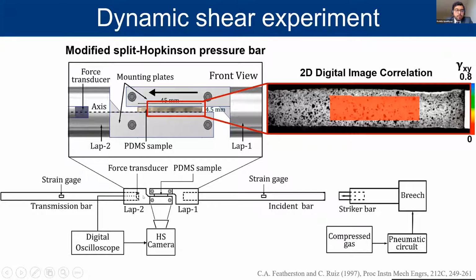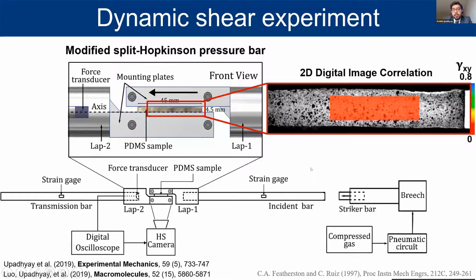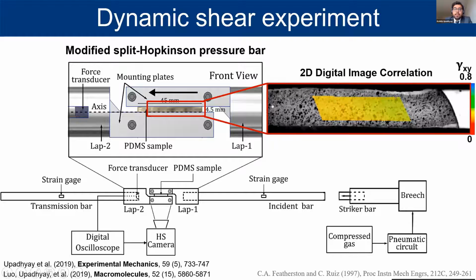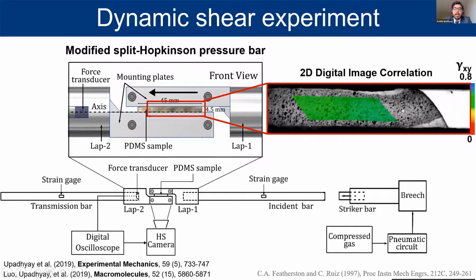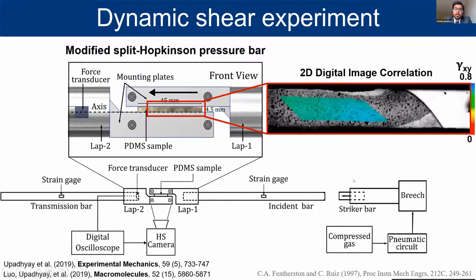In all our experiments, we measure force using the force transducer sandwiched between transmission and lap two. This force transducer also triggers high-speed imaging by the camera. We use 2D DIC to measure the strain in the material, which is a full-field non-contact optical strain measurement technique that tracks the motion of a speckle pattern on the sample. We use black spray paint for this purpose. This video shows the shear strain map in a sample, which is being sheared at 900 per second strain rate.